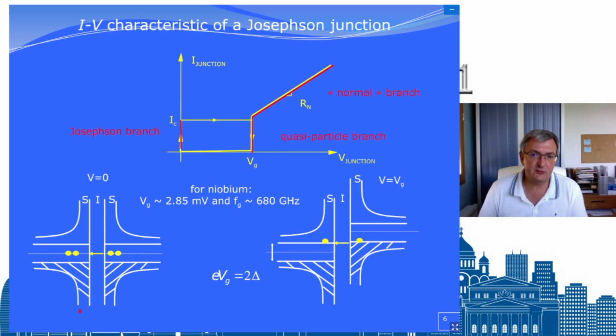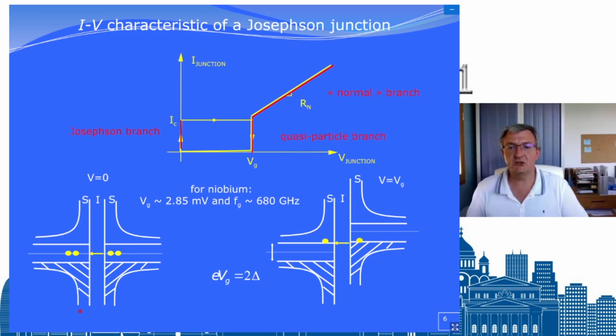The conditions you need to have well controlled really depend on a lot of parameters, not only the Josephson junction itself, how it's fabricated, whether the barrier is homogeneous or not, how is the epitaxy, let's say, of the connections between the different planes, between the different superconductors and the barrier, and also on the electromagnetic environment. Is it clean enough? We can shield the magnetic field more or less, and it will have an influence on this cooling.